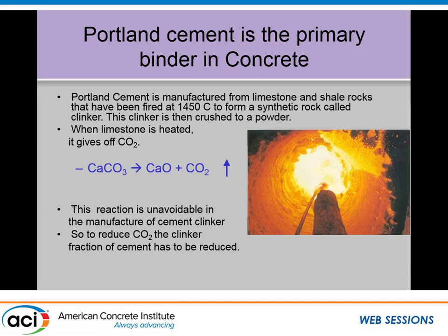Okay. So anyway, this is probably old news for this session, but Portland cement, the biggest issue here is we are calcining limestone, so we're driving off CO2, just taking apart the rock, and we can't avoid that because all our Portland cement systems are calcium silicate based, and the only sources of calcium we have are typically tied to carbonates. We can make the system more efficient in terms of more efficient kilns, and the industry's done that. And they've reached about their maximum thermal efficiency, but now the only way to take things further is to reduce the clinker content in the cement.